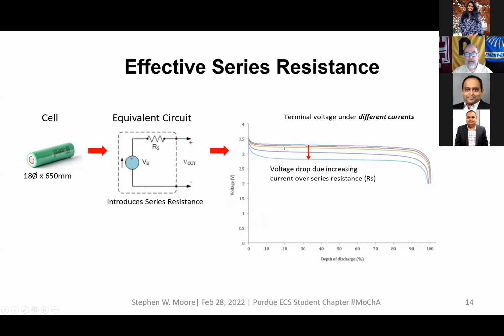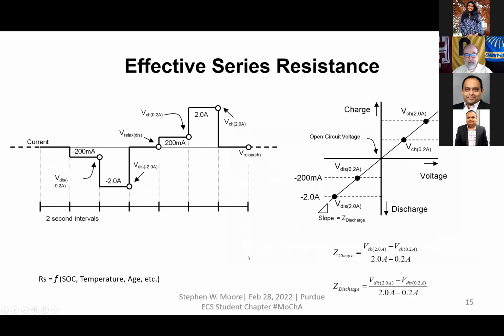And so I can look at an iron phosphate cell, for example, at different discharge currents. And as I have higher current, I get more voltage drop across my series resistance, and my voltage sags. So higher current, higher voltage drop, the more my battery sags. And so this is a very linear approach, and there's a couple of different ways I can find this R sub S. I can apply some test currents to the battery, measure the voltage sag, and characterize what this resistance may be. So we'll look at a few of those examples here.